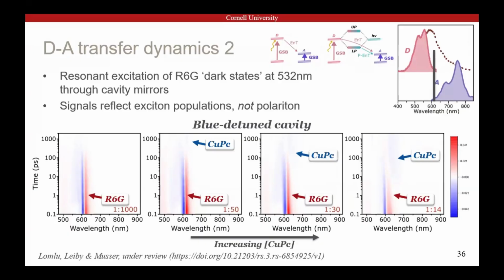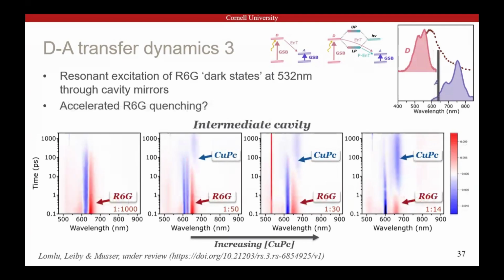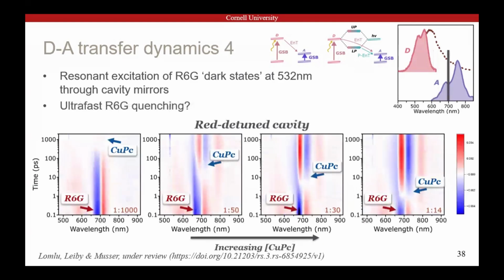It doesn't look like much in this cavity, but as we move our cavity mode redder and redder, the effect gets stronger and stronger until it looks like we're depleting the rhodamine donor in under a picosecond, compared to hundreds of picoseconds for the bare film. So we were wildly excited until we remembered the golden rule of polaritons, which is that they're always going to break your heart, because there are so many artifacts in these things.